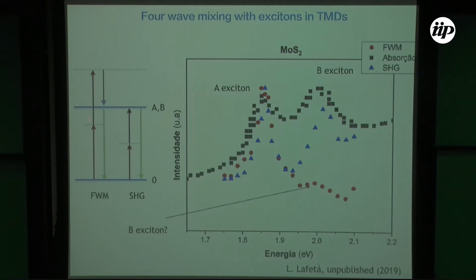And for the four-wave mixing signal, what we do is we have 2 lasers, okay. The first laser, the 2-photon absorption of this one goes to some state with a higher energy than the A and B exciton, and then the other laser excites the excitons in resonance with the A and B exciton, and the emitted four-wave mixing is going to have the energy of the A or the B exciton. Okay, so the four-wave mixing signal as a function of laser energy is these red dots. For the A exciton, you see a strong enhancement, but for the B exciton, you just don't see anything. Okay, we see something, but we are not even sure, so the student is repeating all these measurements.